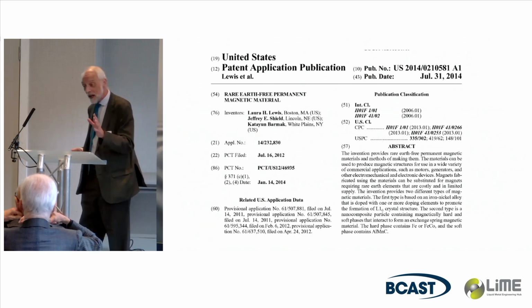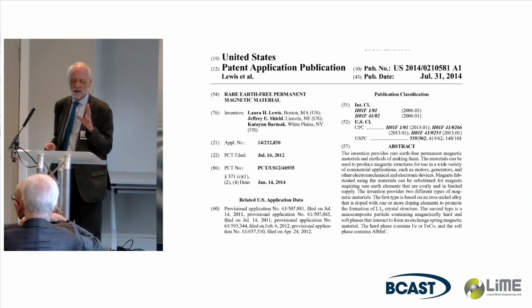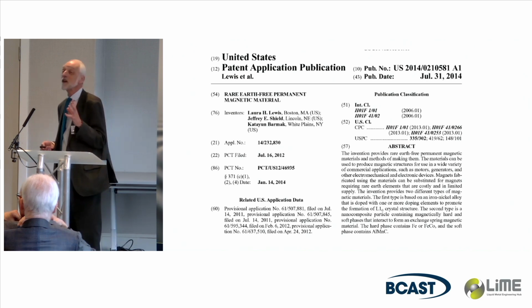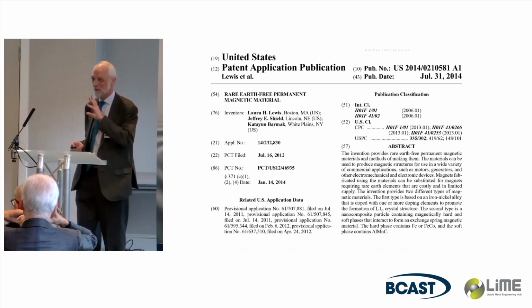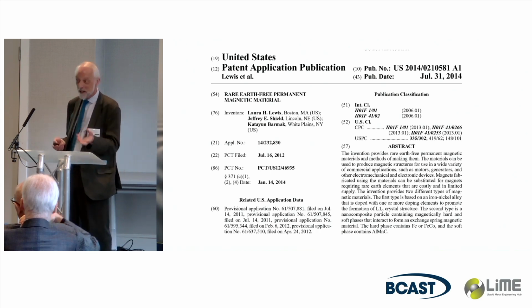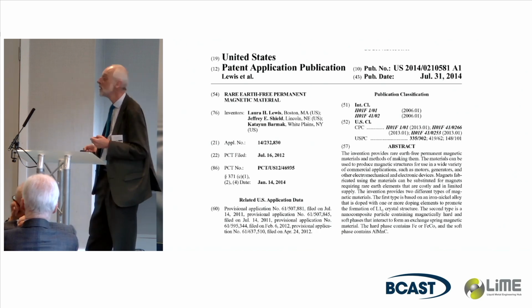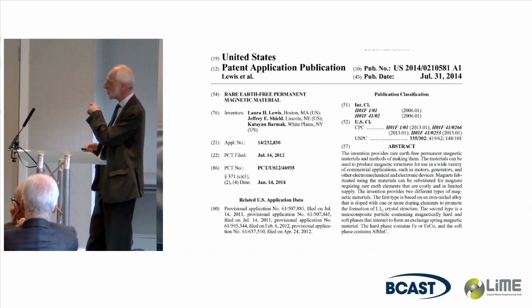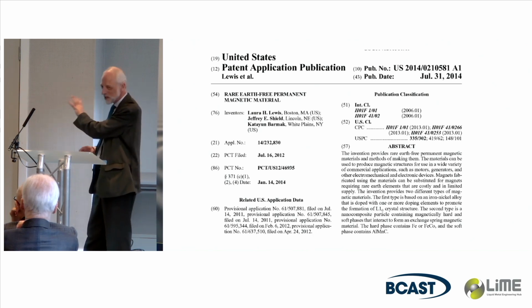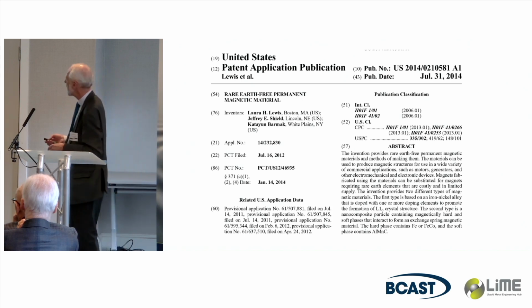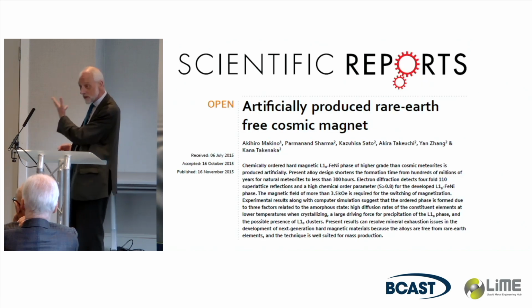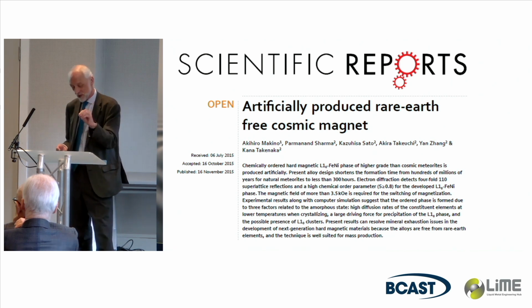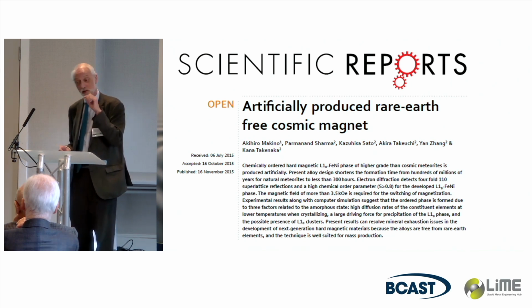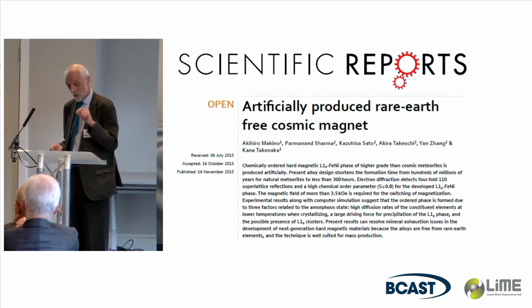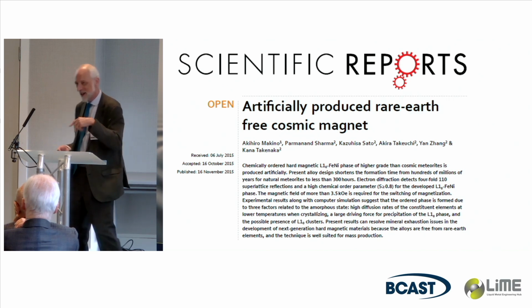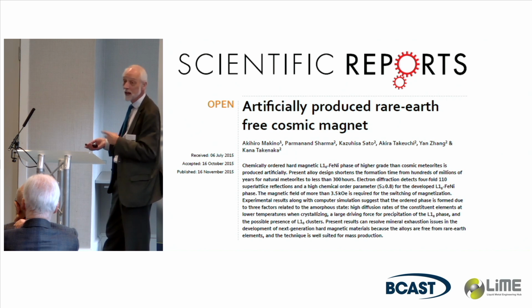People have been trying for decades, trying to do something less worrisome than neutron irradiation to speed up the atomic jumping. They've been doing heavy mechanical deformation, so you artificially promote the population of vacancies. And it's fair to say that none of this work has actually led to tetrataenite, but many attempts. This is another attempt, thinking, well, if we grew a crystal at a low enough temperature, maybe it would grow originally in the ordered structure, and it wouldn't have to order from the FCC. And one way to do that would be to grow it in a metallic glass.